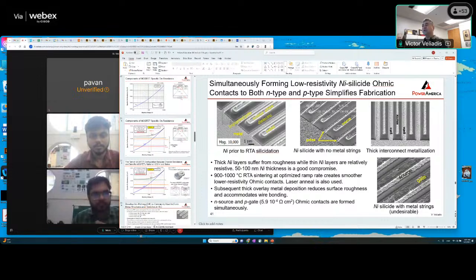Now, if you leave it longer, when it comes to manufacturing, anything that takes a longer time is more costly, right? There's more labor. So I have found that that's the right amount of time to form silicide with the rapid thermal annealing method. Okay, so when you do the front along the process, you do the RTA, you create the silicide in the front layer, you do all the ohmic contacts in the front, but then the drain in a vertical device is in the back of the wafer. So that you do at the very end.